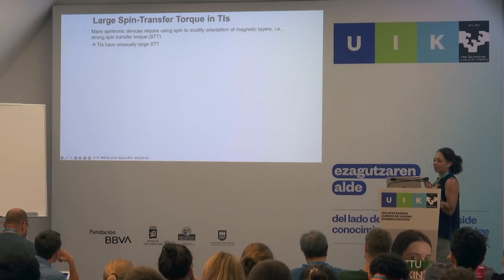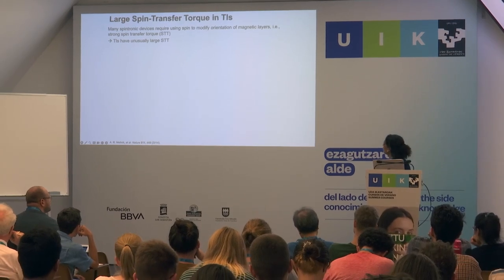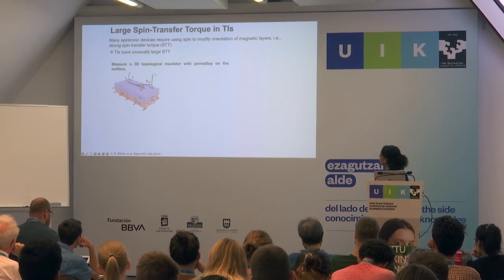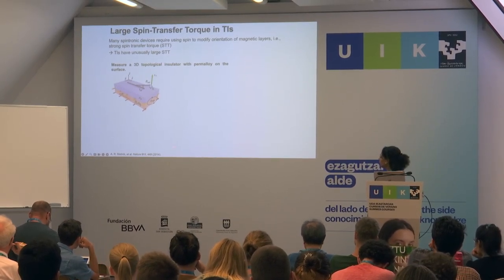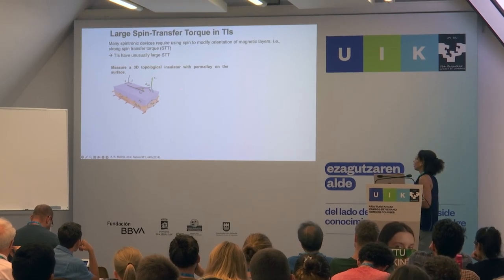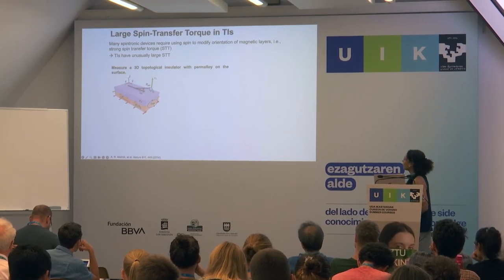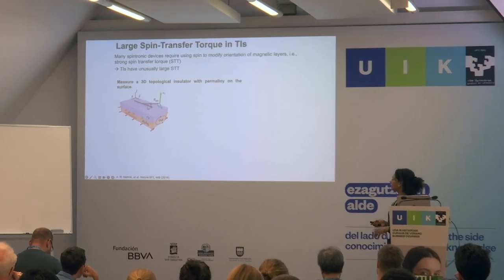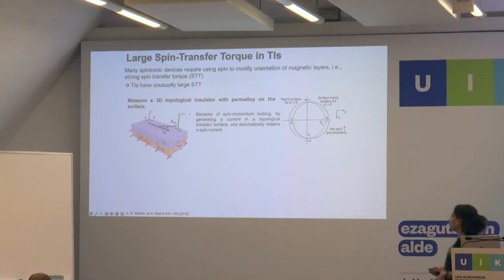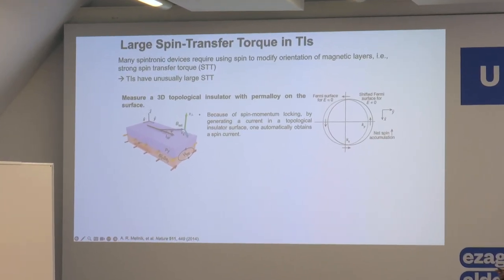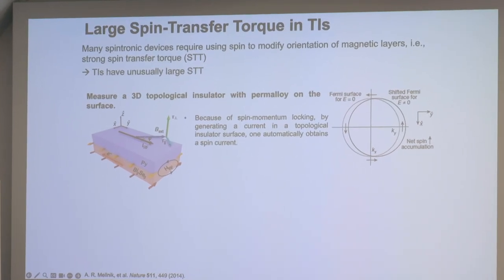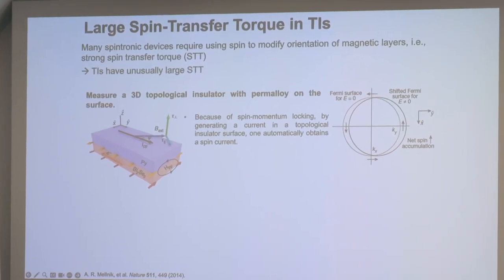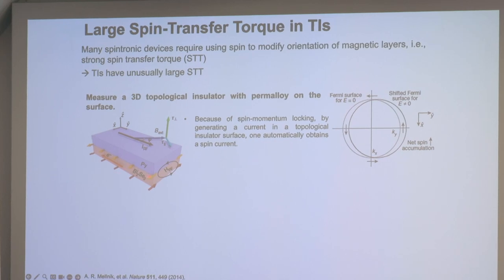It's basically the Edelstein effect, which creates a spin imbalance here. So TIs have unusually large spin transfer torques. This is measured by these experiments in Dan Ralph's group, where they showed that if you take a 3D topological insulator and put a magnetic material like permalloy on the surface, because of the spin momentum locking, again, you get a spin imbalance. When you put an electric field across it, you get net spin accumulation on the surface of the TI.